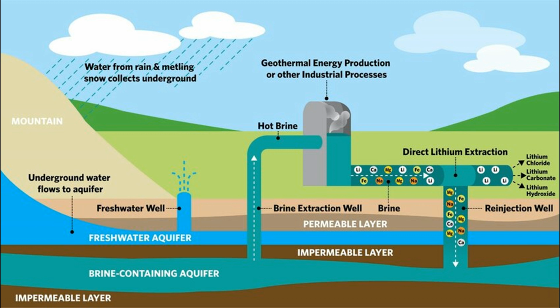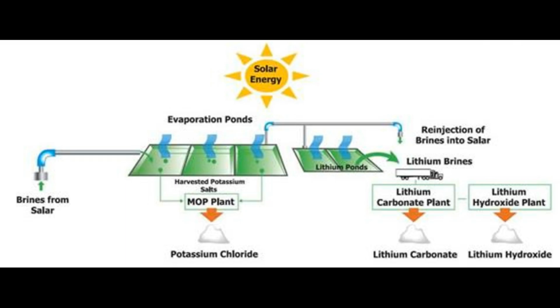Lithium recovery via adsorption. Lithium selective ion exchange sorbents are a promising alternative for extracting lithium from brines. Inorganic ion exchange sorbents, such as lithium manganese oxides, spinel lithium titanium oxides, and lithium aluminum layered double hydroxide chloride, have been shown to have high capacity for selective lithium uptake. However, the recovery process requires the lithium to be in contact with these sorbents for long periods of time. Additionally, sorbents can be very expensive. They are mostly available as powders that require energy-intensive processes for lithium recovery and can degrade during the acid-driven desorption process.